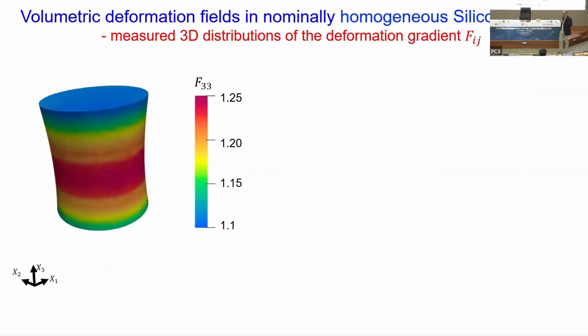Okay, so no surprises here at all, because these are very macro measurements. Let's go now to look at what the field looks like in 3D, because we have now done these measurements in 3D. Now, these are real measurements. These are not simulations. These are the sorts of volumetric fields that we are measuring. What I'm talking to you about here is F33. What do I mean by F33? It is the deformation gradient in the axial direction that we are pulling the specimen. So what 1.25 here means is that it is 25% strain.